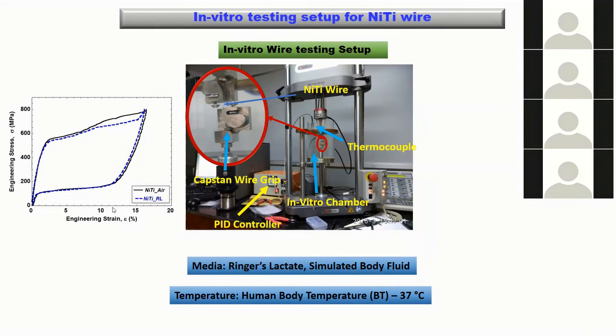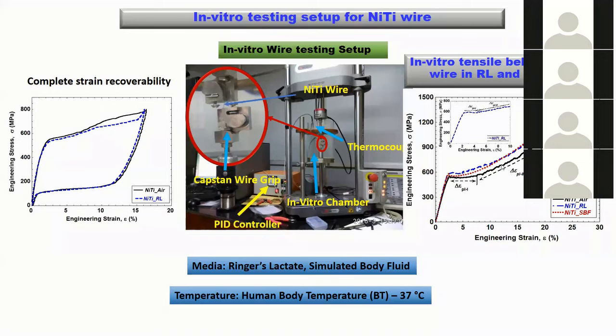And what we have seen is that, in this example, the black curve is without the chamber and the blue one is in the presence of Ringer's lactate. In both cases, the material has shown perfectly pseudoelastic behavior. It has stretched up to a certain extent and then upon unloading, it has come back to zero. So we can see complete strain recoverability.